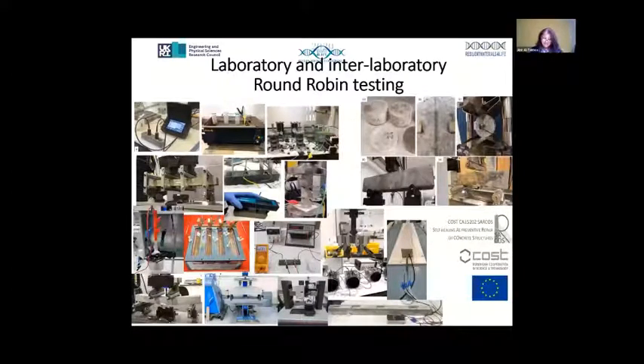In terms of laboratory testing on the cementitious samples, this clearly starts with the introduction of the damage, so crack initiation or exposure to aggressive environments, cyclic loading, aggressive chemicals, freeze thaw, and others. And then we carried out specific tests to monitor and assess the recovery and progress and performance of the healed material. We tested compressive strength, fracture strength, sorptivity and permeability, electrical resistivity, chloride ingress, and a range of corrosion-related tests. And we usually combine a mix of conventional and bespoke tests, and we've also used non-destructive testing.